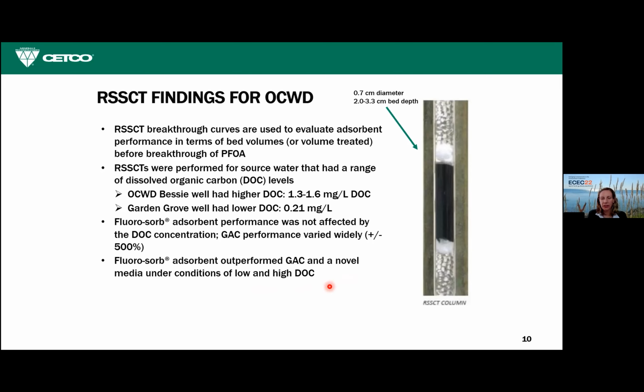This is specifically because with GAC, other dissolved organic carbon compounds compete with PFAS for sorption, and that is not the case with Fluorosorb, which is specific. The surface modification is specific for PFAS. So if you're okay with not adsorbing dissolved organic carbon, then Fluorosorb is a great adsorbent for PFAS because the DOC just goes right through.